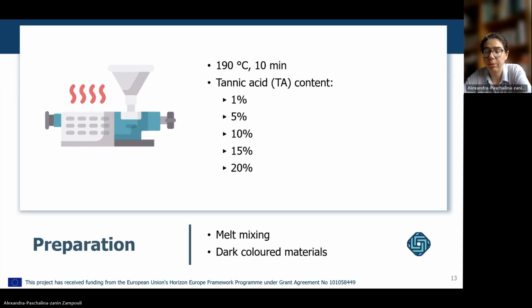Materials were readily prepared by melt mixing at 190 degrees. The materials were mixed for 10 minutes. And with the exception of the composite containing 1% of tannic acid, which was light brown, most materials were dark colored, almost black. And the tannic acid contents that were studied ranged from 1 to 20%.